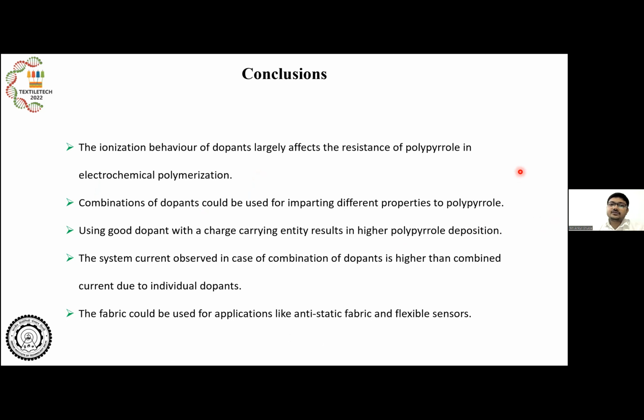So we concluded that the ionization behavior of the dopants largely affects the resistance of polypyrrole in electrochemical polymerization. The combinations of dopants could be used for imparting different properties to polypyrrole. Using a good dopant with a good charge carrying entity, in our case sodium nitrate, results in higher polypyrrole deposition and thereby lower resistance of the polymer.